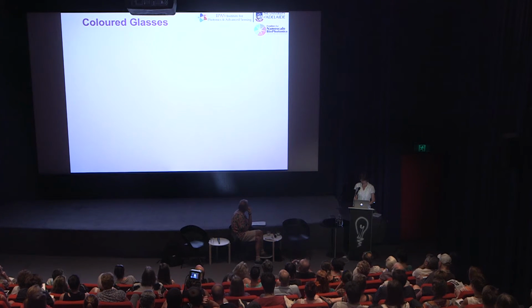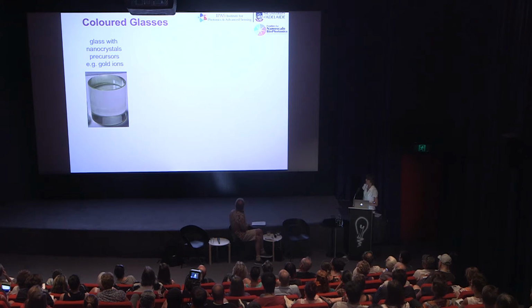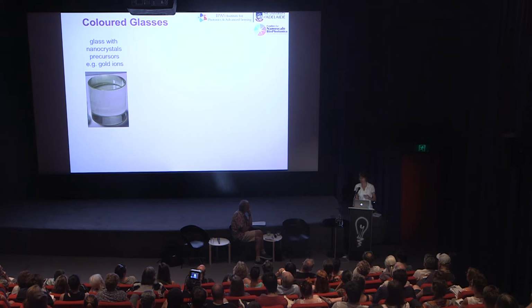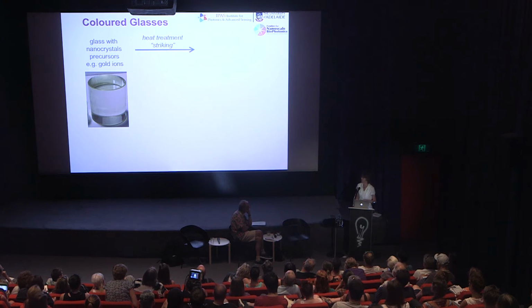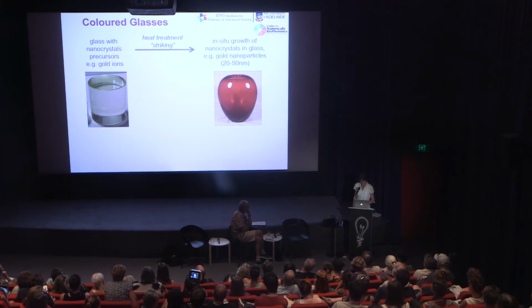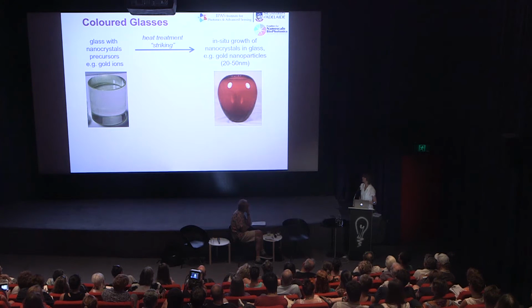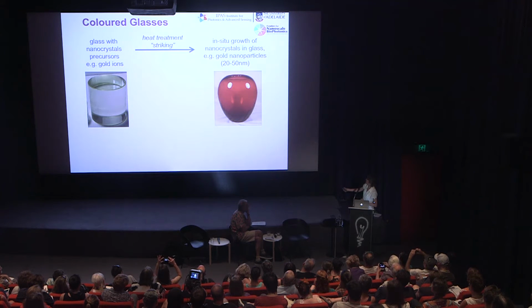So how are these glasses made? What's happening is that one first makes a glass which has precursors. So the glass doesn't have the nanocrystals yet, but precursors that can then be formed into the nanoparticles. For example, glass that contains gold ions. Gold ions themselves don't have any color, and so therefore one can achieve a colorless glass. Then in the heating treatment, or as glass artists say, in the striking, the gold ions are turned into gold atoms, and then they grow into nanoparticles, and then they create this beautiful color.